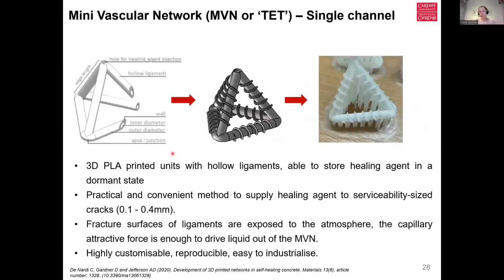So welcome to the mini vascular network, the MVN or TET, as sometimes you'll hear me refer to them. These are single channel 3D polymer lactic acid printed units with hollow ligaments, which are able to store healing agent in a dormant state. They are 3D printed, as I mentioned, and they are filled with the healing agent and sealed with a silicone plug. They provide a practical and convenient method to supply healing agent to serviceability size cracks, so from 0.1 to 0.4 millimeters, although they break particularly well at 0.3, and that's been the focus of our design.